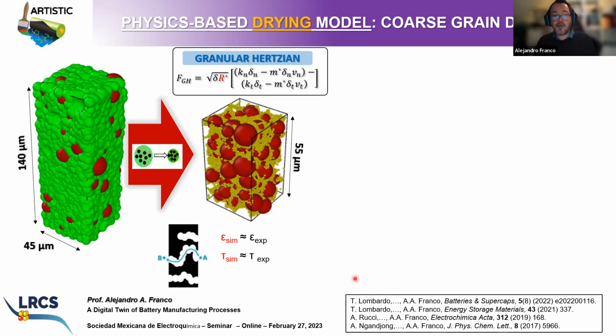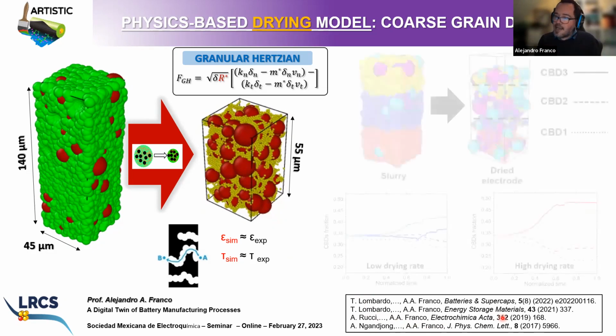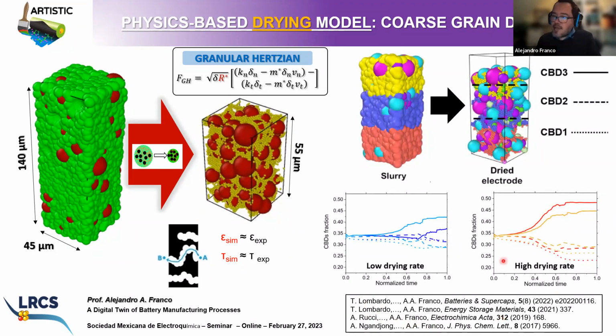And he was in charge of modeling the electrochemical performance of this electrode being generated by this simulator of the manufacturing process. And since then, we have also had a lot of progress in the methodology. One of these progresses is that now we are able to simulate the impact of the drying rate on the electrode microstructure in order to capture the influence of drying rate on the CBD migration phenomenon, which is a phenomenon widely known in battery manufacturing.